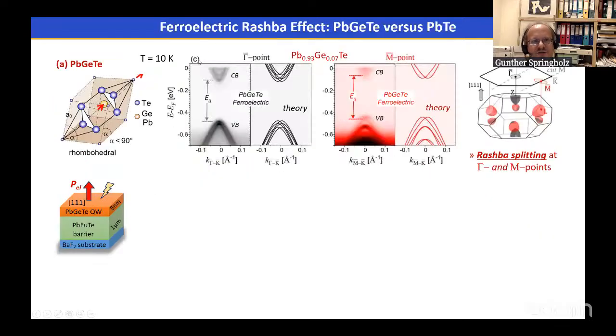Now I would like to speed up here a bit. So we have measured the ferroelectric Rashba effect in lead germanium telluride, as is shown here by this experimental data. So IV-VI semiconductors have a many-valley band structure, as shown here on the right-hand side. So the band extrema at the L point of the Brillouin zone, and we have one along the ferroelectric polarization direction, which is called the Z point, and we have the M points, which are the projection of the oblique valleys to the surface Brillouin zone, as indicated here in the schematic diagram.